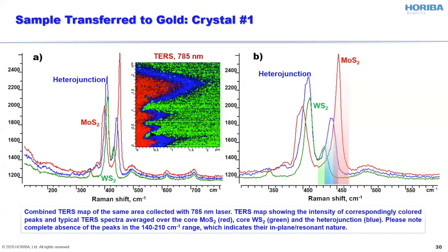Again, we collected a nice TERS map. We can see all the same features in terms of the morphology, so the varied width of the transition area in this lateral heterostructure, but the spectral signature is quite significantly different. Now, as you can see, there are no peaks around 200 wave numbers. All of them are gone. The only peaks left in the TERS spectra collected with 785 nanometers are the main A prime peaks for tungsten disulfide and molybdenum disulfide, and this peak that characterizes the alloy as well.